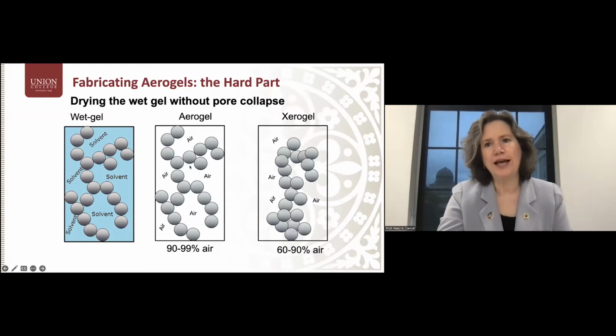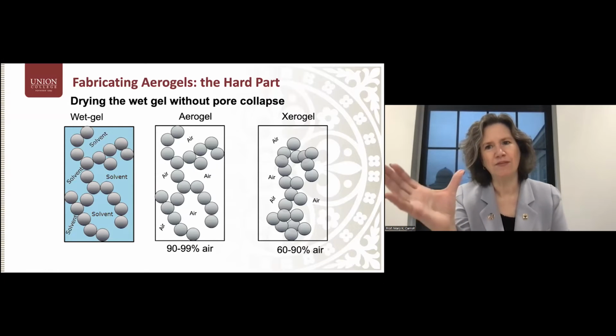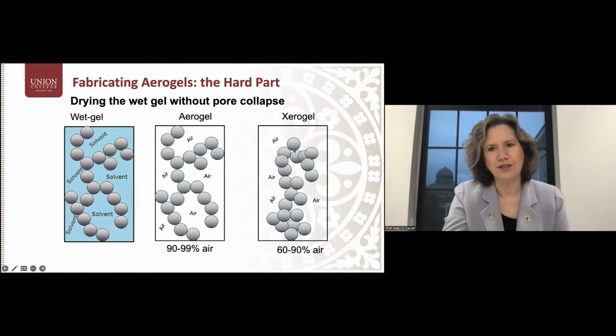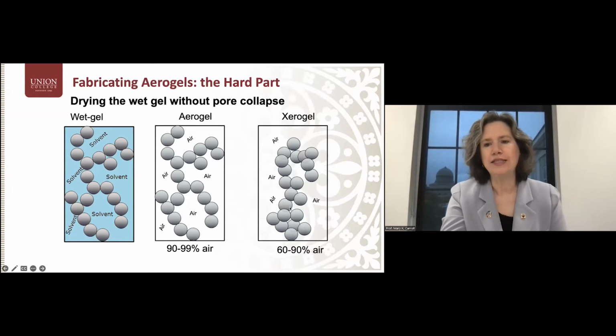If, on the other hand, we let this material dry under ambient conditions, if we let the solvent evaporate, the solvent evaporating will cause issues with capillary action and surface tension and collapse to some extent the pores, leaving us, if we let it dry all the way, with a xerogel. This is a Greek prefix for dry gel, that still is porous, but has a collapsed porous structure. And so the difficulty is getting the solvent out without having pore collapse.